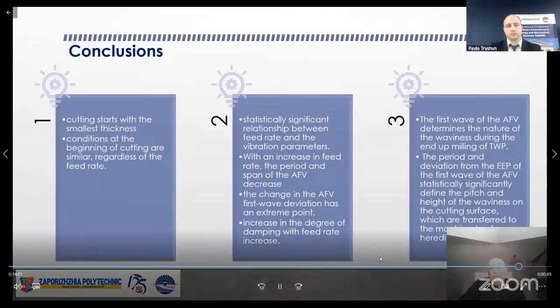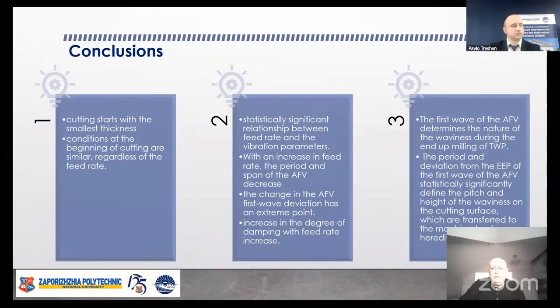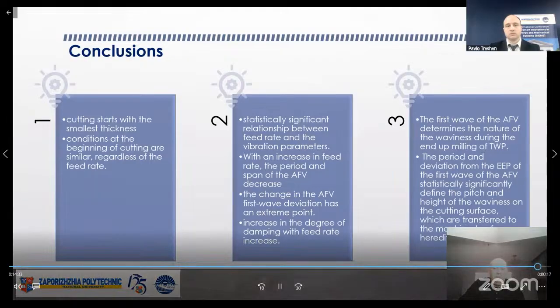The first wave of the AFV determines the nature of the waviness during the end-up milling of thin-walled parts. The period and deviation from the elastic equilibrium position of the first wave of the AFV statistically significantly define the pitch and height of the waviness on the cutting surface, which are transferred to the machined surface as heredity.